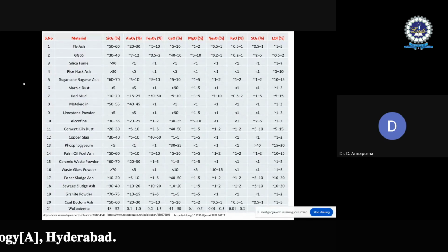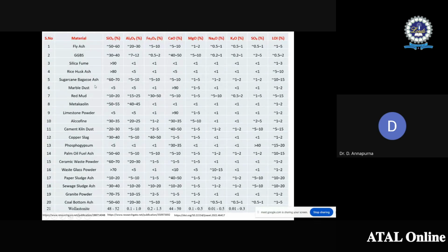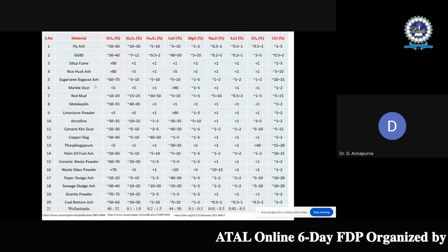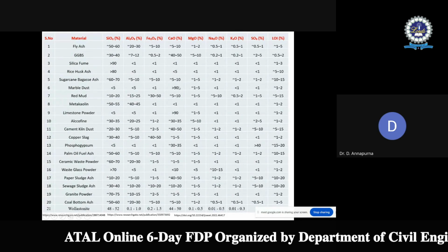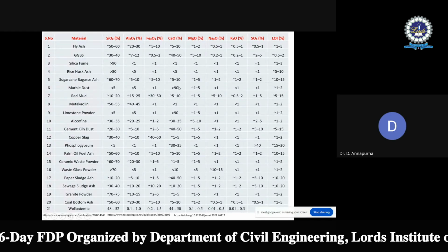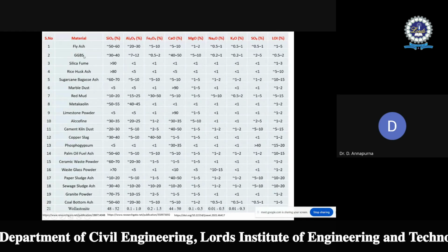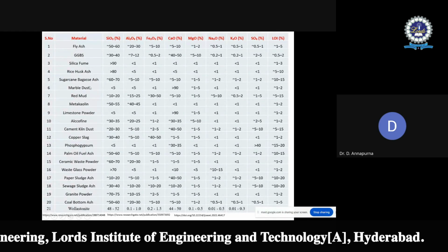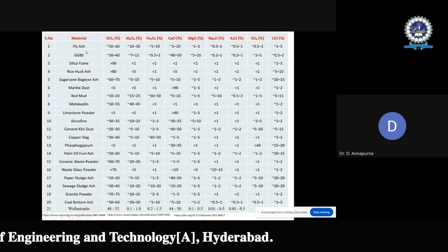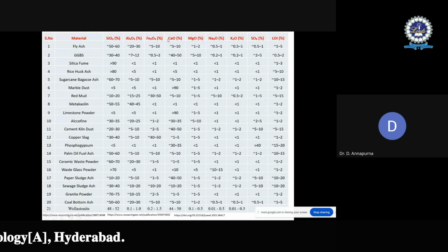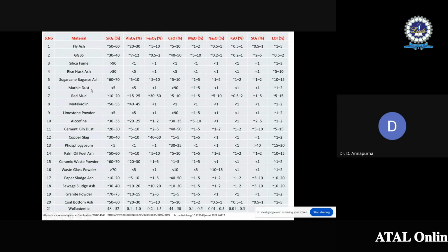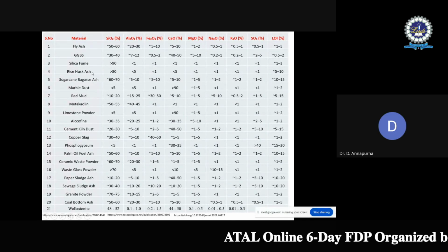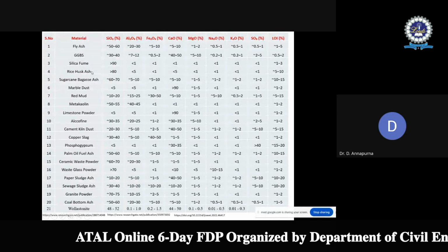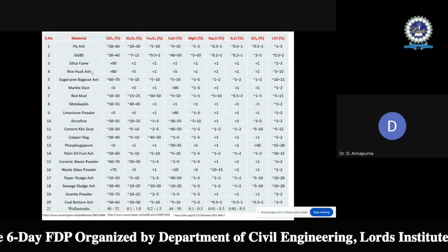Then comes marble dust. Marble dust also can be used as a precursor or source material because it has a high amount of calcium oxide. Compared with GGBS, the cost of marble dust will be less. If we are going to have a combination of silica, alumina and calcium oxide, then we can try this marble dust combination with sugarcane bagasse ash, rice husk ash, etc. to prepare alternative geopolymer concrete.